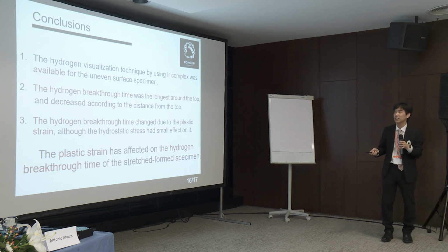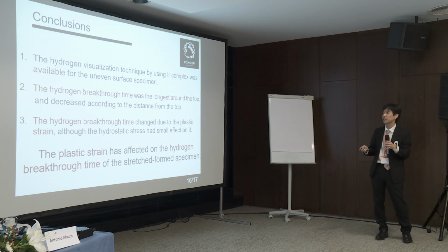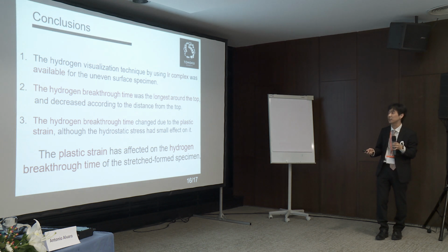I would like to conclude today's talk here. The hydrogen visualization technique using iridium complex was available for an uneven surface specimen, such as a stretch-formed specimen. The hydrogen breakthrough time was the longest around the top and decreased according to the distance from the top.